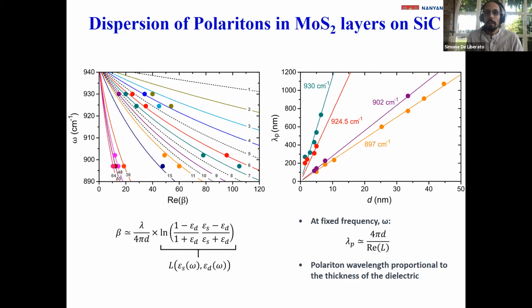Yes. You need to have access to the dispersion of the phonons, but given that those are well-known materials, yes, you can use different kinds of approaches, both numerical and analytical, to get fairly precise results. We actually were able to quantitatively fit the dispersions in crystal hybrid studied by the group of Joshua Caldwell, and we obtained a quantitative fit. So given that those are well-known materials, it should be possible to get quantitative results. Okay, so I will read the paper, and then if you need, I can contact you.